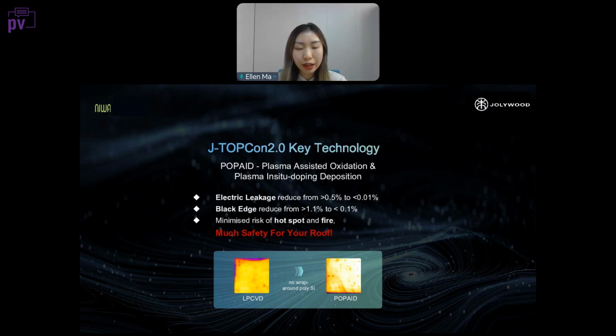And we've talked a lot about the advantages at the cell level. So what about at the module level? Compared with TOPCon 1.0 technology, the 2.0 technology will reduce the electricity leakage from more than 0.5% to less than 0.01%. The back edge leakage will reduce from more than 1.1% to less than 0.1%. Those will successfully minimize the risks of hotspots and fire, which means for the end customer, it will be much safer for your roof.